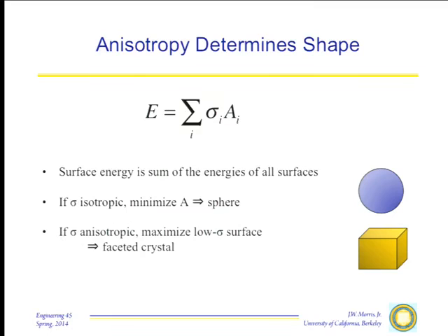And for that reason, when you see something that you look at immediately and you say, aha, this is a crystal because it's got all these well-defined surfaces on it, this is why. Not that it's more crystalline than a metal, it's more anisotropic. And that's usually because ionicity in the compound makes you have a very, very strong tendency towards surfaces that are electrically neutral. So you can very often just look at the crystal structure and predict what the shape of the crystal is going to be.